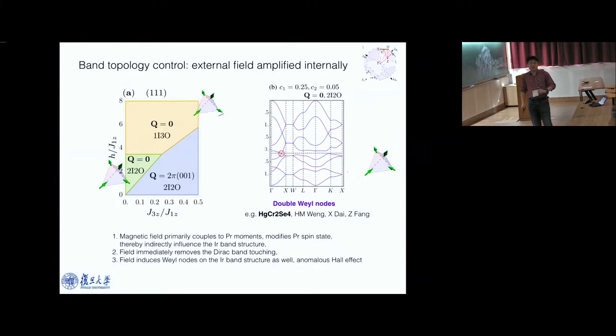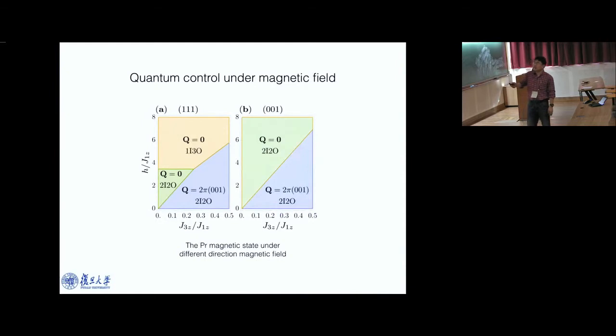And this is actually a double Weyl semimetal. It's not a conventional Weyl node. This Weyl node has a quadratic dispersion along two momentum directions and linear dispersion along one direction. This is a double Weyl node. It also has an anomalous Hall effect if you measure the Hall effect. You can also apply the field along another 001 direction, and you can have a different magnetic state and a different band structure topology for the conducting electrons.